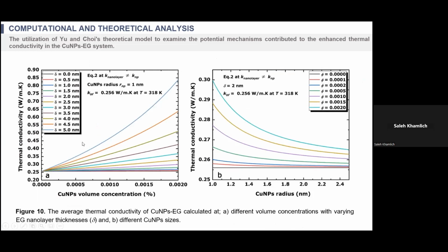So these results are coming from that model of Yu and Choi. It shows clearly that by increasing the concentration and also increasing the thickness of the layer, we found that if the thickness of the layer is 0, there is no enhancement. By increasing the layer thickness around the nanoparticles, when I'm speaking about the layer, I'm speaking about the adsorbed molecules of the ethylene glycol around the copper nanoparticles.